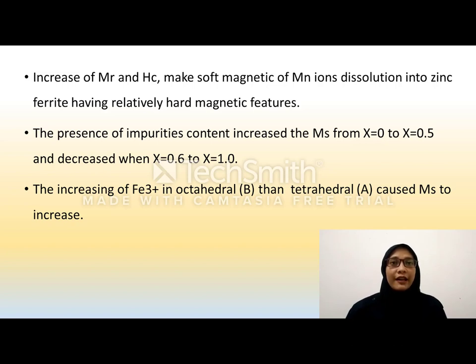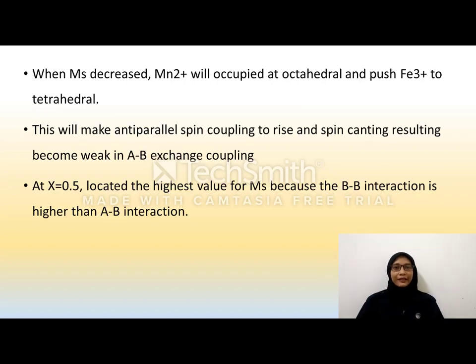The increasing of Fe3+ in octahedra rather than tetrahedra causes saturation magnetization to increase. When saturation magnetization decreases, Mn2+ will occupy octahedra and push Fe3+ to tetrahedra. This will make antiparallel spin coupling rise as spin canting results in weak A-B exchange coupling. At X equals 0.5, the highest value of saturation magnetization is located. This is because the B-B interaction is higher than the A-B interaction.